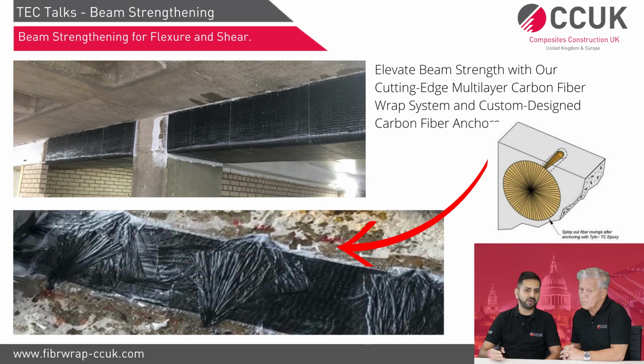confinement at the underside is quite simple. You can put another layer of U-wrap to confine that FRP, but on top it's very difficult because you've got a slab there. So in that instance, we use the anchors as we explained on the previous slide. We drilled a hole through the slab, gone onto the web of the beam, and then applied the anchor all the way through. So that's how we applied a hoop there to confine the FRP. So that's how these anchors were used.